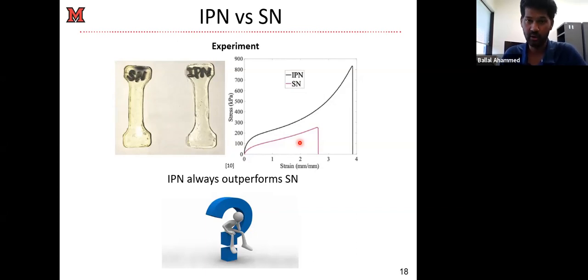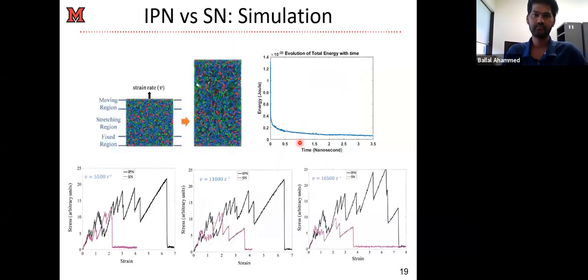So let's see what we have got out of MD simulations. This is our tension test specimen, like a normal tension test, the way you do it in the molecular dynamics simulation. You define a fixed region, you have a stretching region, you define a moving part, and you apply the strain rate or tension, and you allow the material to stretch, and you record the stress and strain. And you see that in our case also, we found that the IPN outperforms the SN. We have the same kind of range.